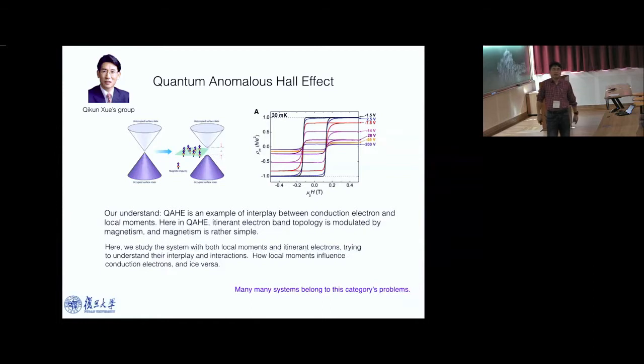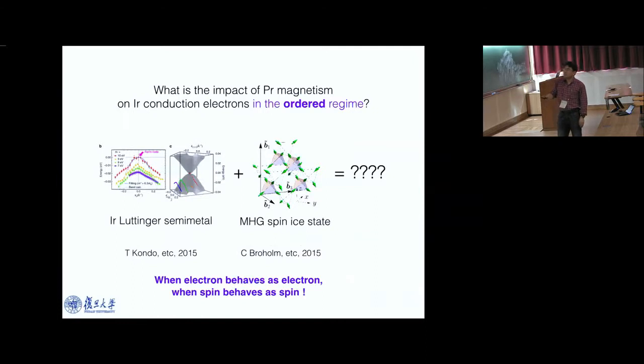Really, this is an example, a very special and interesting and simple example of how conducting electron interacts or interplays with local moment. In this particular context, the conducting electron is a simple Dirac electron, and the magnetism is a trivial ferromagnetism. Both of them are rather simple, but if we put this simple Dirac electron with this trivial ferromagnetism, you obtain this remarkable phenomenon of quantized anomalous Hall effect, right? So in our context, the conducting electron is a crystalline symmetry protected Luttinger semimetal, and the local moment is this complicated 2 in 2 out non-collinear spin-ice magnetic order. So both of them are kind of non-trivial. If you put them together, the outcome has to be even more non-trivial. So it has to be something non-trivial.